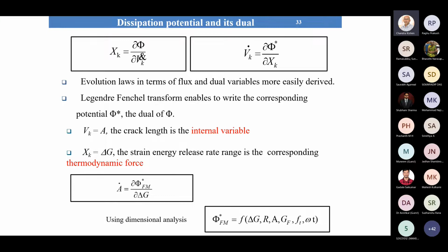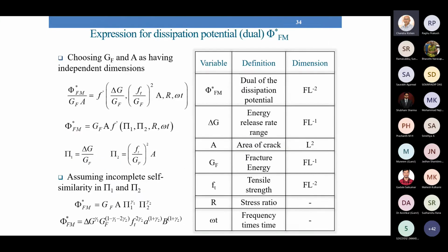Then we have the geometry properties, that is the area of the crack. Then we have the material property parameters, the fracture energy, or the fracture toughness, and the tensile strength. So we have included all these factors. These are the different variables which we have used, and these are their dimensions. Through dimensional analysis, we could obtain an expression of this type for the potential.